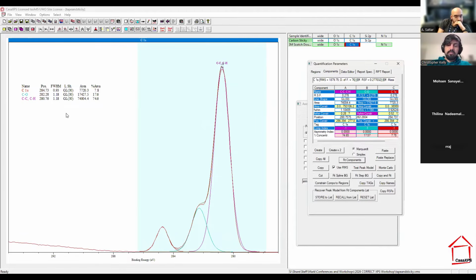Now, as I mentioned, this sample is insulating and we're using a charge neutralizer to correct that, so this peak is not where it should be. This peak should be somewhere around 284.8, 284.5, something, or 285. But it's not. It's shifted downward to 280.7. And so we want to shift that peak up.